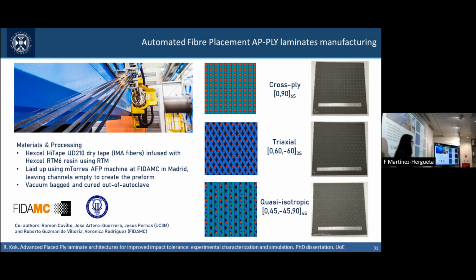The panels were manufactured in carbon fiber epoxy, but we used dry tows that we then infused with the resin on our vacuum bath. We manufactured cross-ply and quasi-isotropic laminates as before, but we also include a third configuration, a triaxial configuration, 0, 60, and -60.